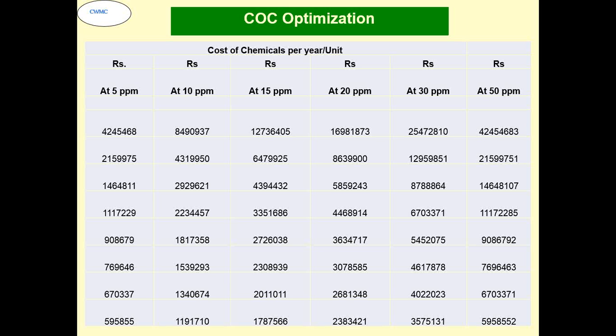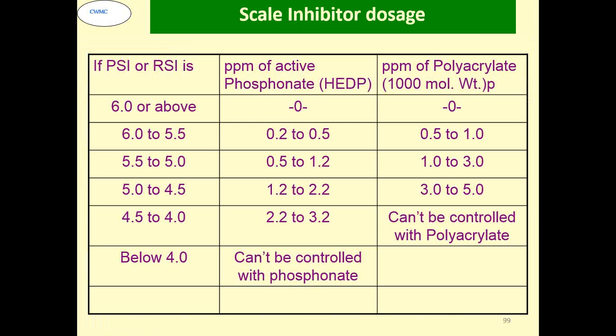This is the cost of chemical per unit that has been calculated. Now this is the generally acceptable levels of dosages that are given there. HEDP, which is again a common scale inhibitor, at the RSI of 6 to 5.5, you can go to 0.2 to 0.5, 5.5 to 5, you can go to 0.5 to 1.2. Similarly, 5 to 4 RSI, you need to do between 2.2 to 3.2 ppm of HEDP.